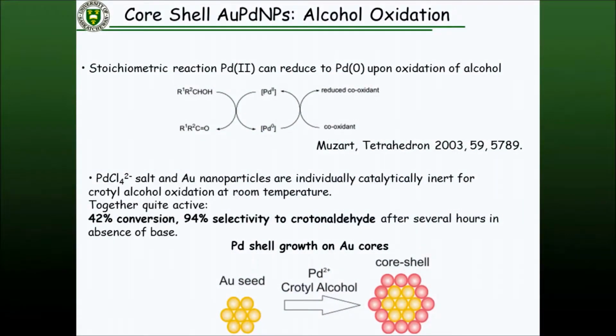It turns out there's a lot of literature on people playing with allylic alcohols with palladium, and palladium-2 salts actually react with allylic alcohol stoichiometrically. It's a 1-to-1 reaction: you get the aldehyde, you get palladium 0, which usually gives you palladium black. Mark Lawton in Toronto actually did his PhD on this stuff way back when, so this is old chemistry. It's a stoichiometric reaction, not a catalytic reaction, and in fact that's what we see by just using the pure palladium salts.